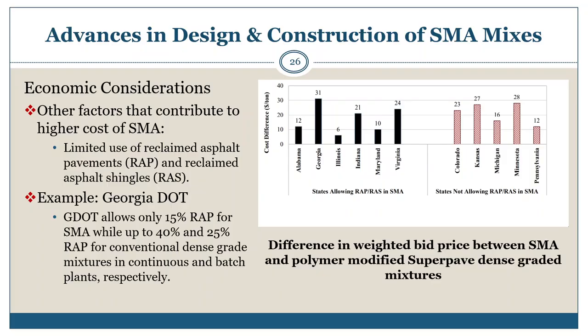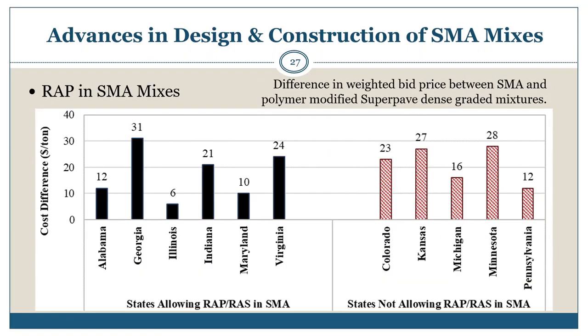As an example, Georgia Department of Transportation allows only 15% RAP for SMA, while it also allows up to 40% and 25% RAP for conventional dense graded mixes in continuous and batch plants, respectively, as shown on the slide. This slide simply shows an expanded version of the bar graphs on the previous slide.